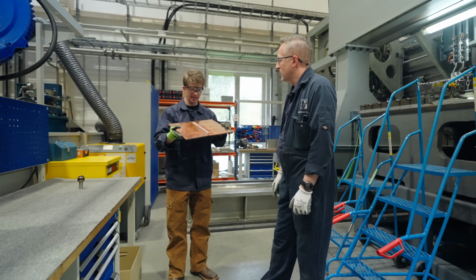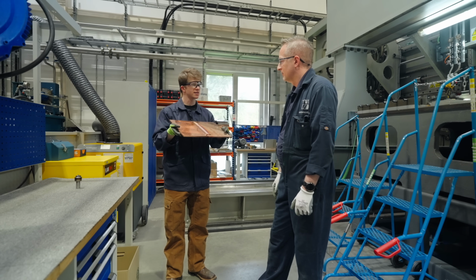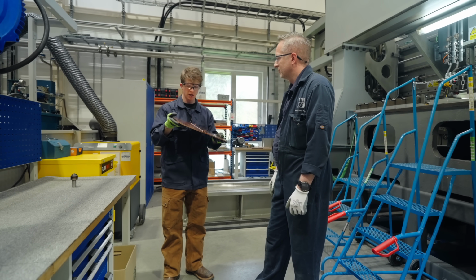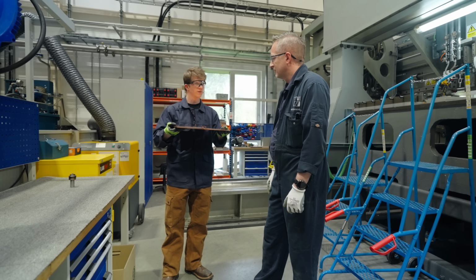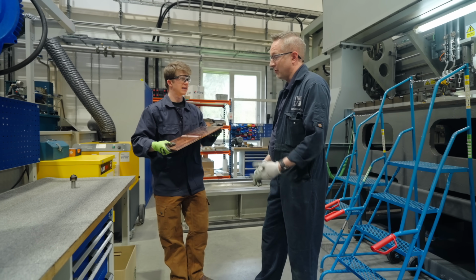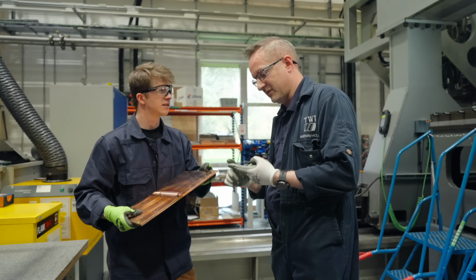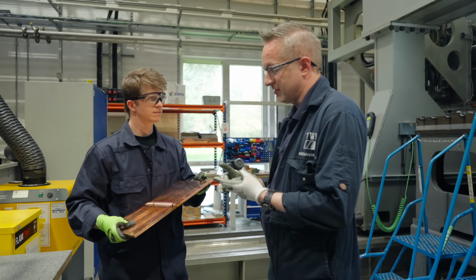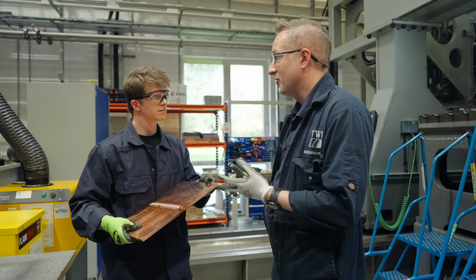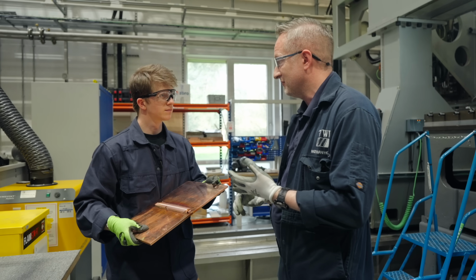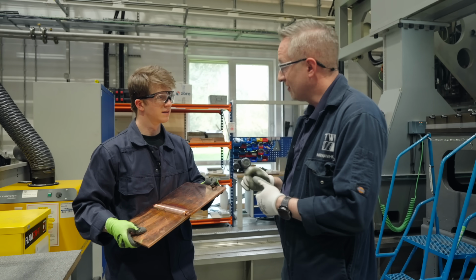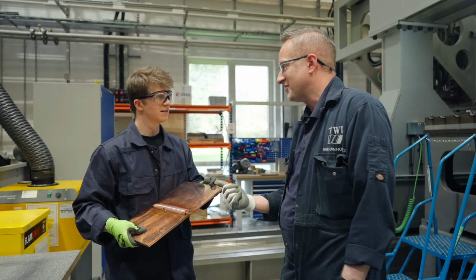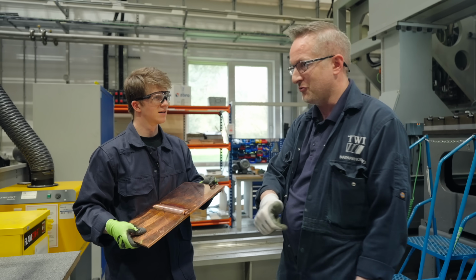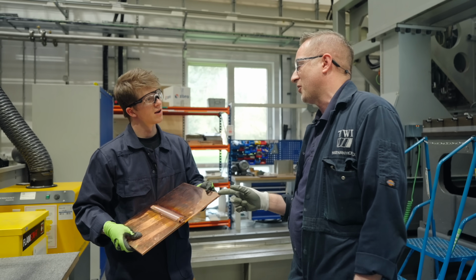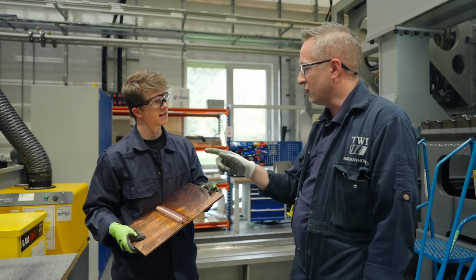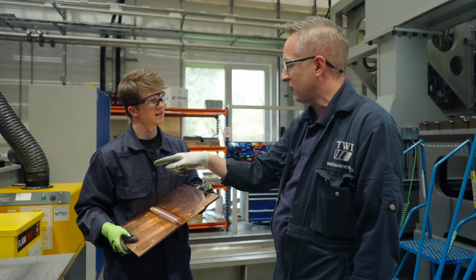Typically it's excelling when you're using plates and sheet metals. What's the sort of range that you can friction stir weld and what sort of metals? So I've friction stir welded all aluminium variations, magnesium, you can friction stir weld titanium, steel, copper, you can friction stir weld brass. Wow. Now you can't friction weld brass, but you can friction stir weld brass. Interesting.